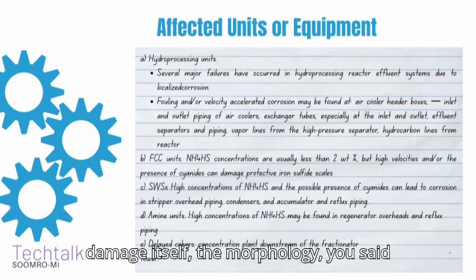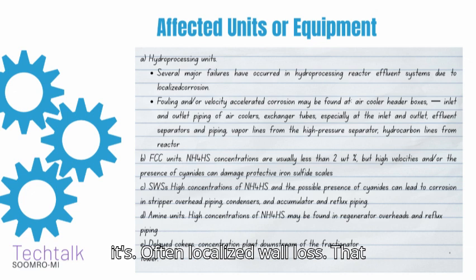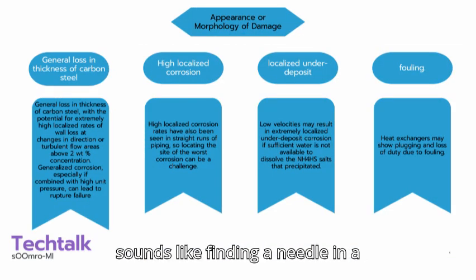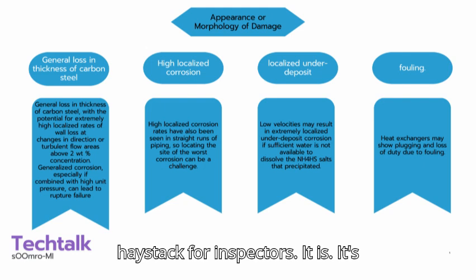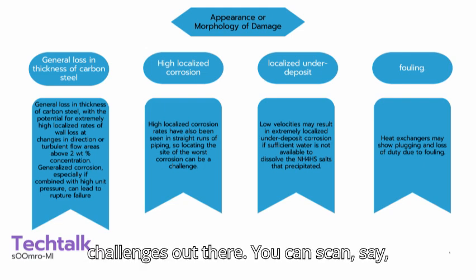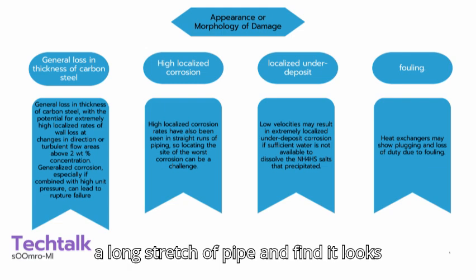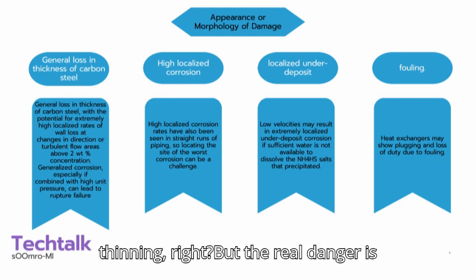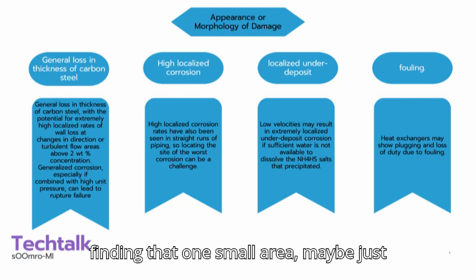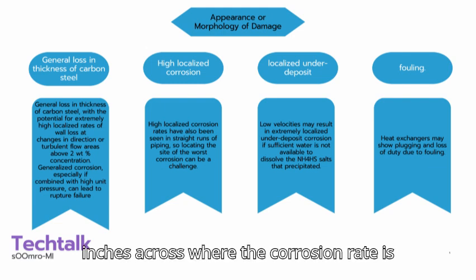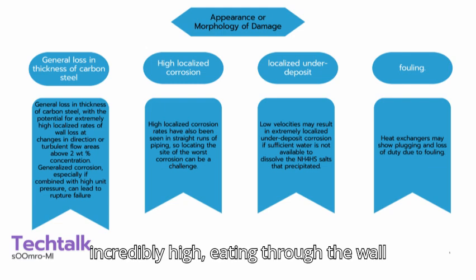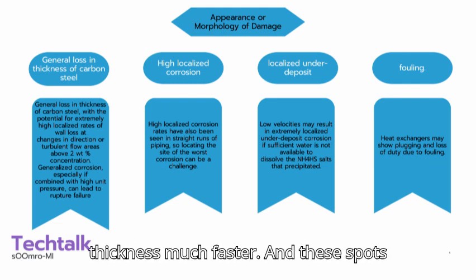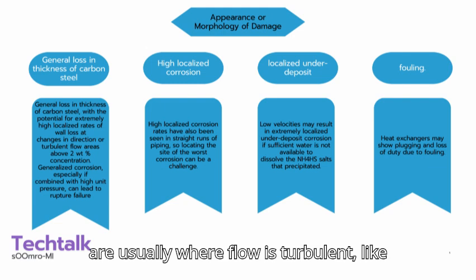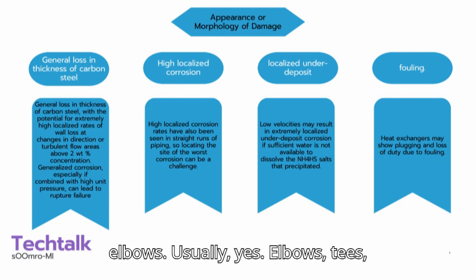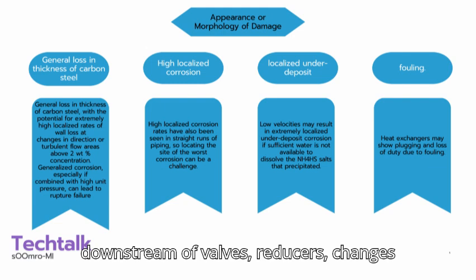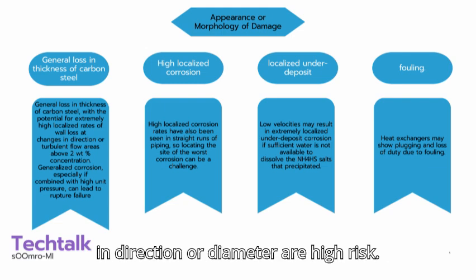Now, looking at the damage itself, the morphology, you said it's often localized wall loss. That sounds like finding a needle in a haystack for inspectors. It is. It's arguably one of the toughest inspection challenges out there. You could scan, say, a long stretch of pipe and find it looks perfectly fine, maybe just some general thinning. Right. But the real danger is finding that one small area, maybe just inches across, where the corrosion rate is incredibly high, eating through the wall thickness much faster. And these spots are usually where flow is turbulent, like elbows. Usually, yes. Elbows, tees, downstream of valves, reducers, changes in direction or diameter are high risk.